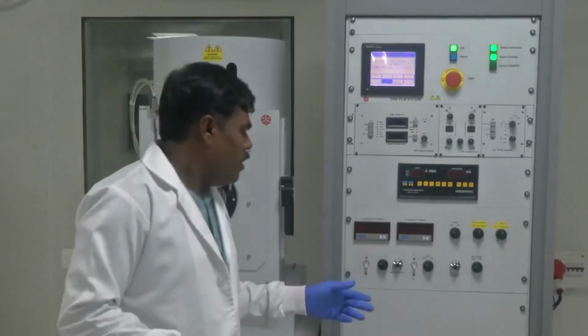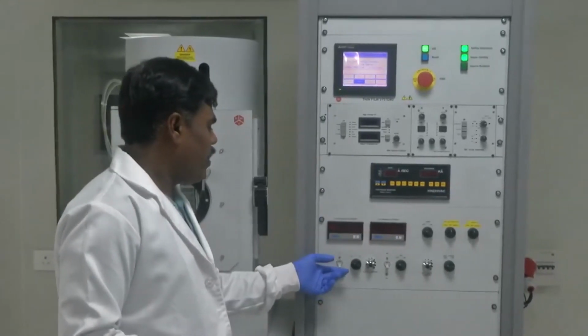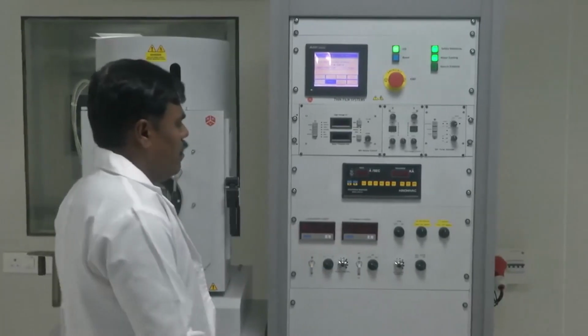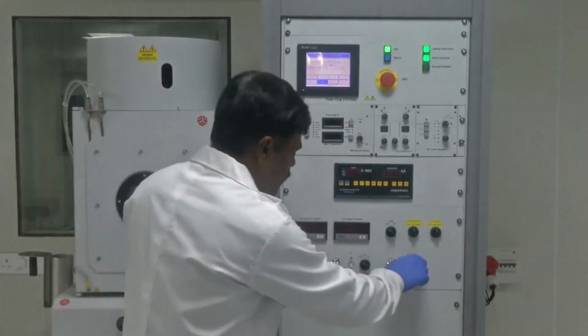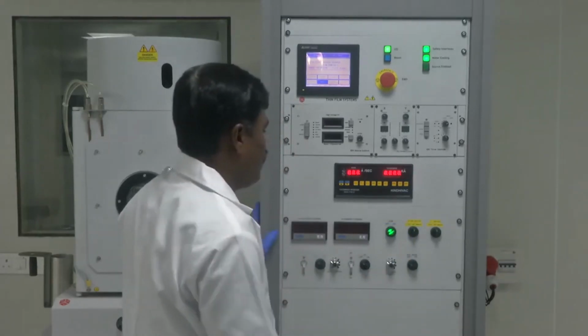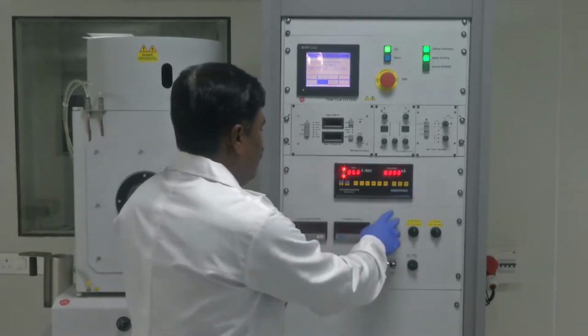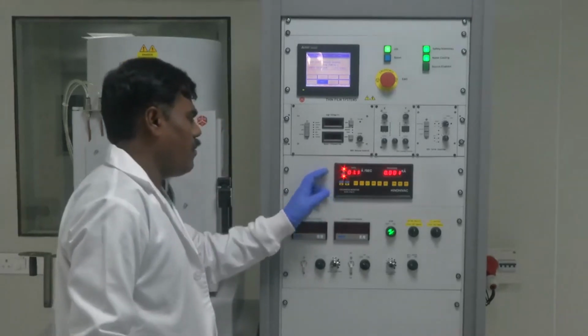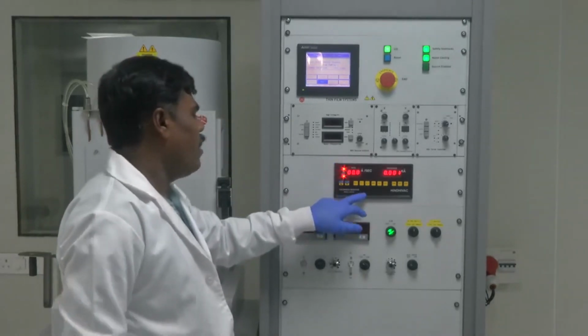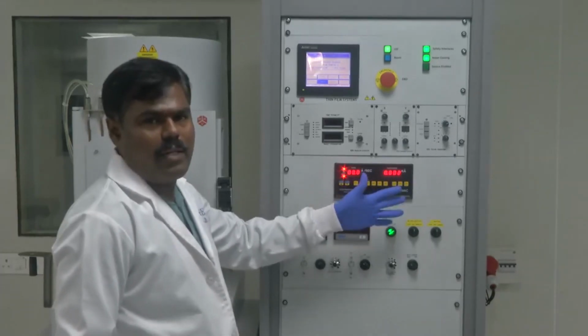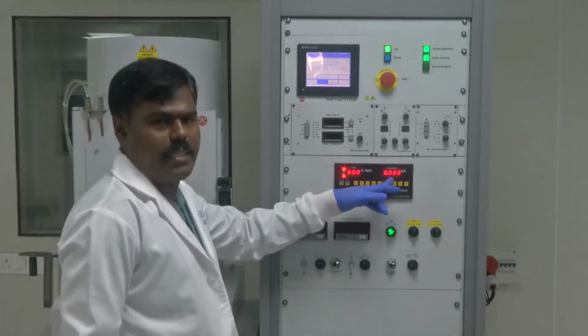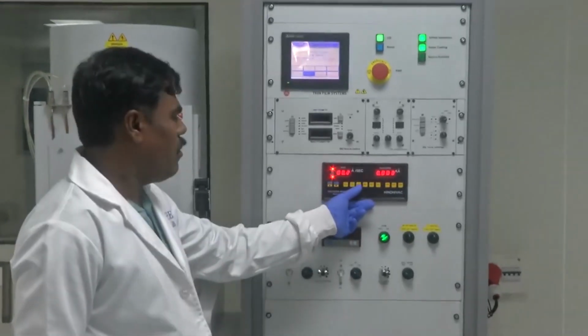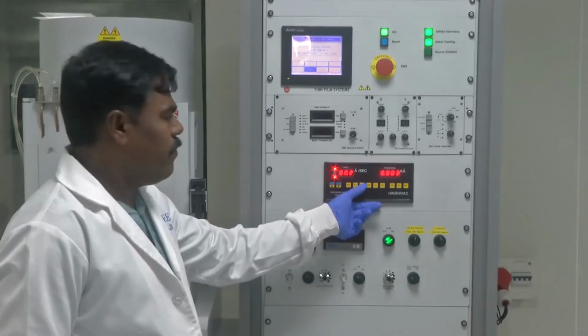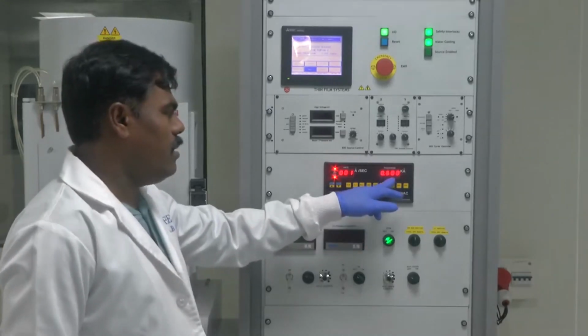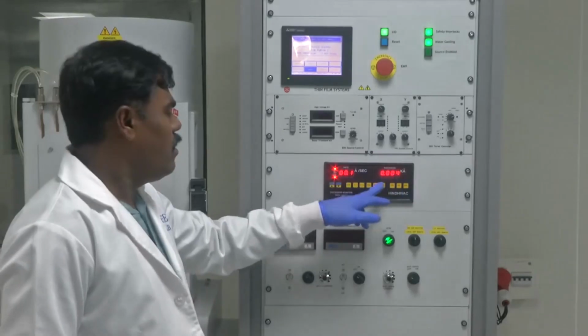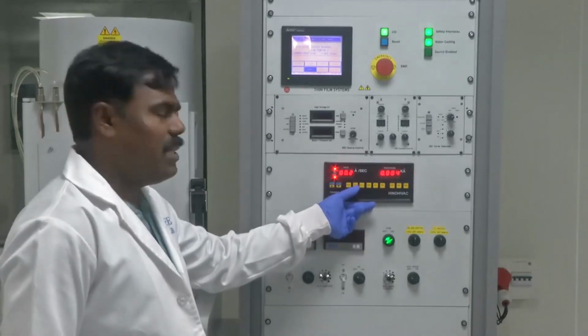Before we do the thermal deposition, switch on the digital thickness monitor. After switching on the thickness monitor, set the thickness you need using TL1 or TL2. It is already set at 600 nanometer. Like this, whatever you need, please set the thickness.